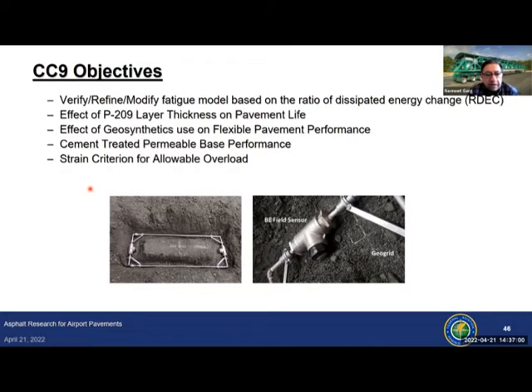We are looking at performance of cement-treated permeable base. And then there are two sections where we are looking at the strain criteria for allowable overload, because in the ICAO standard, for flexible pavements, 10% overload operations are allowed. And again, that 10% number was pulled out of the air. There is no research behind it. So we did some tests in our construction cycle 7, and we are doing it again in 9 to see how many overload operations you can really allow before your pavement starts seeing significant damage. And we are using these bender element sensors that were developed by Dr. Erol Tutumluer at UIUC. So they have been installed to quantify the localized stiffness increase around the geogrid layer.